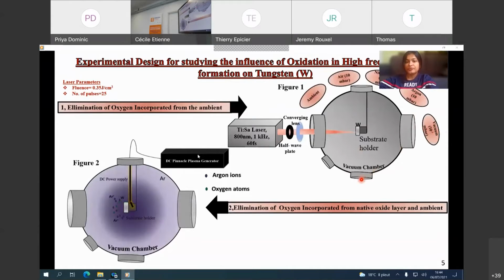So very high vacuum. And when we are doing this experiment under vacuum condition, it ensures the elimination of oxygen incorporated from the ambient. But we still have the topic of native oxide layer to address, or we still have to eliminate the role of the native oxide layer. And this can be achieved by using a technique called sputtering. So in figure 2, you can see how this is done. We have the vacuum chamber, and we fill the vacuum chamber with argon gas, and then we provide a DC power supply, and it creates argon ions which sputter off the tungsten native oxide layer from the tungsten surface, and hence will give a native oxide layer free surface, and thereby elimination of oxygen incorporated from the native oxide layer and ambient is possible. So all these experiments, with sputtering and without sputtering, and all the irradiations under all the different gaseous conditions are done for the same laser parameters.